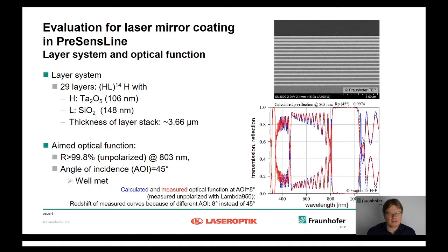Here you see the layer system. It's a typical lambda quarter stack, 29 layers, tantalum oxide and silicon oxide, total layer thickness 3.66 micrometers. The aimed optical function was 99.8% for unpolarized light at 803 nanometers, angle of incidence 45 degrees. We met this optical function.